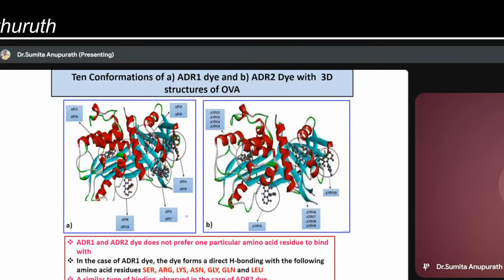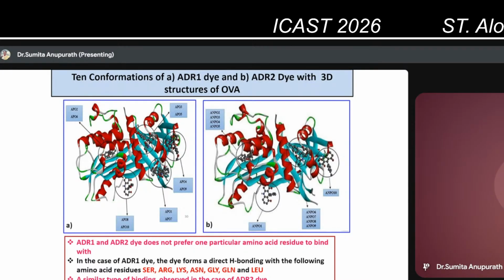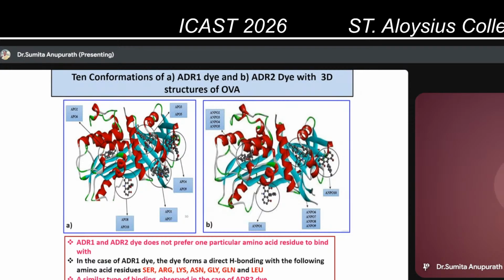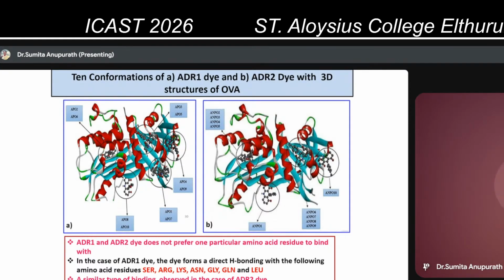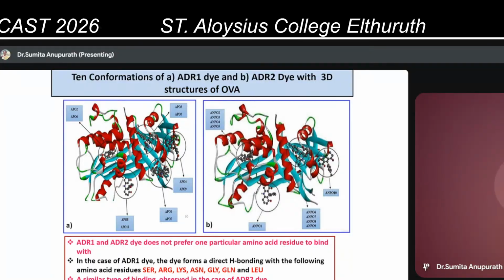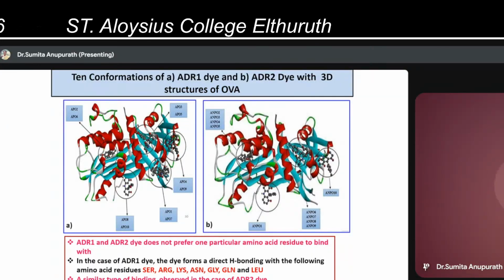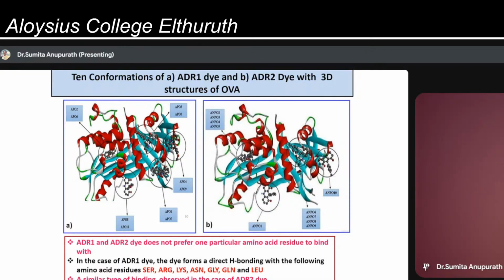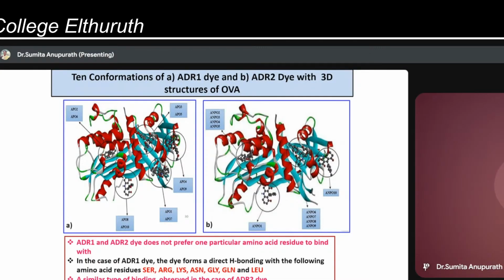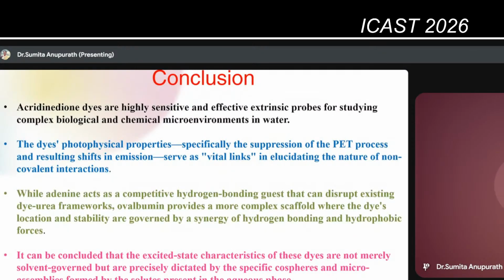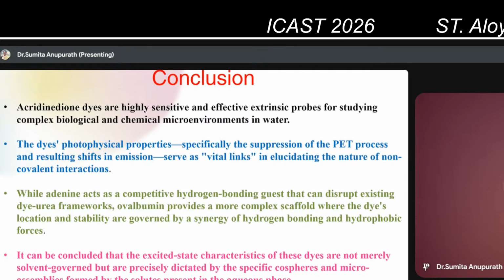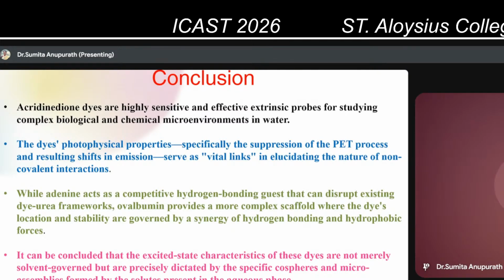So the 10 conformations of ADR1 dye and ADR2 dye with the ovalbumin suggested that the dye does not prefer to bind with only one particular amino acid residue. It binds with various amino acid residues. It can go and occupy deep inside the ovalbumin, the hydrophobic region, or it can also bind to the exterior part of the ovalbumin, which is more hydrophilic in nature. And such similar binding was observed in the case of ADR2 dye also. So to conclude my work, I can say that acridine dione dyes are highly sensitive and effective extrinsic